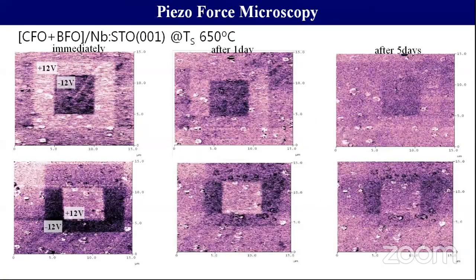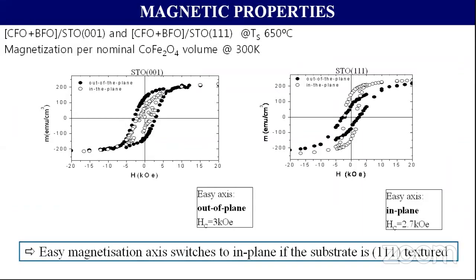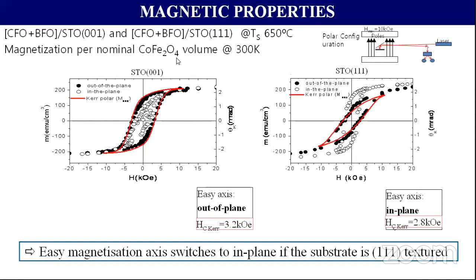And this is the piezo force microscope. This clearly shows that the prepared films are ferroelectric material, and the ferroelectricity remains even after 5 days. So this clearly shows that it is a robust ferroelectric material with ferromagnetic property at room temperature. This confirms that it has multiferroic properties at room temperature. This is the magnetization and also the Kerr, complementary magnetic measurements, which clearly show that we can switch the easy axis from 001 to 111.